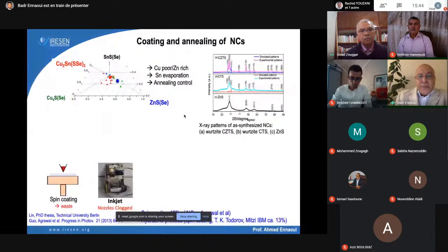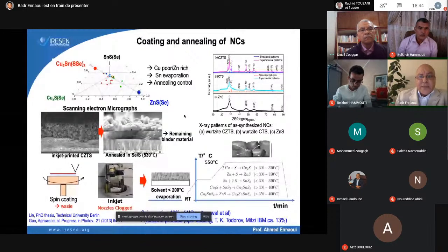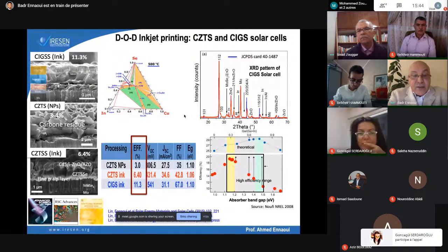Here I will move on and show you this result. You see here some results where we have made copper zinc tin sulfide nanoparticles. We have made copper zinc tin sulfide ink and copper indium gallium sulfide. This means we use the method of hot injection. That's what you see here in black. In red, we have used the same material, but with the metal precursors. And the third one, we have used copper indium gallium sulfide.